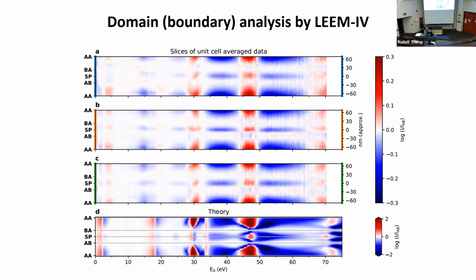And when you compare it to theory, you see that there's very strong correspondence between the theory and the experimental results, right? And that means, as I showed you, when you measure the intensity as a function of energy, you can extract atomic structure. And that's what we do here. So we extract the atomic structure both in the AA region, where they sit on top of one another with that out-of-plane lateral shift that agrees very well with the theory, and in the region here where you go from AB to BA, that's a narrow region with its own unique structure, and again we can determine the atomic structure on that. So this allows you to determine atomic structure on really small length scales that otherwise would be difficult to do using these very low energy electrons.